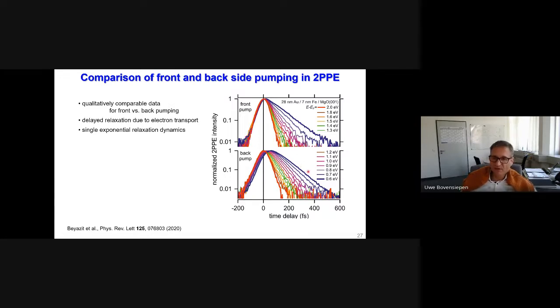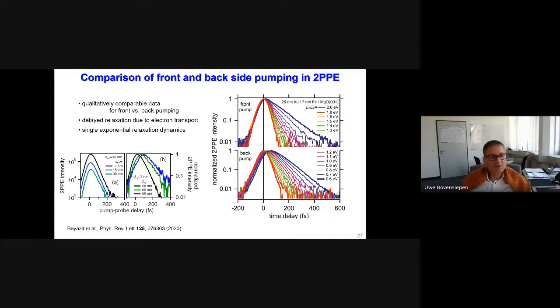Where the front side and the back side pumping differ is here in the build-up of the intensity. So here you see that there is a delay for the lower energy, which you can also see here at the maximum, which is absent for the front side pumping. So here we can directly identify those transport effects that I've mentioned to you on the last slide. Just as some additional information, if you vary the iron layer thickness, so this is constant gold layer thickness, variation of the iron layer thickness, we see a drop in the injection efficiency of the electrons from iron into gold. So here simply the intensity goes down.